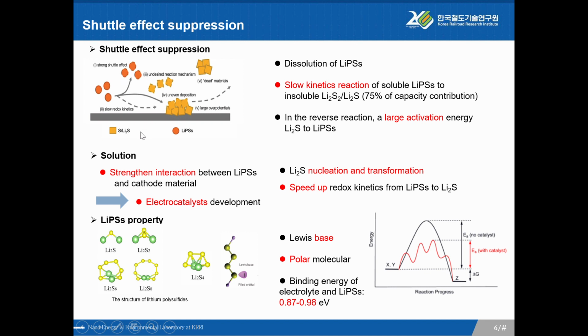How to solve the shuttle effect? So first we should strengthen interaction between lithium polysulfide and the cathode material. Second, we should increase the lithium sulfide nucleation and transformation. And the last one is to speed up the reduction kinetics from lithium polysulfide to lithium sulfide. So catalyst development satisfies all the requirements. So what kind of catalyst can be applied into lithium-sulfur battery? In other words, what factors can determine the catalyst?